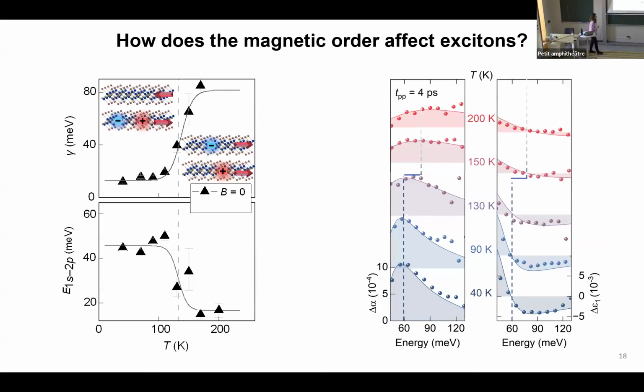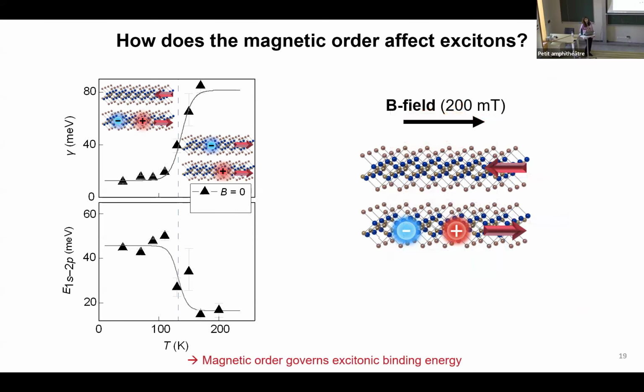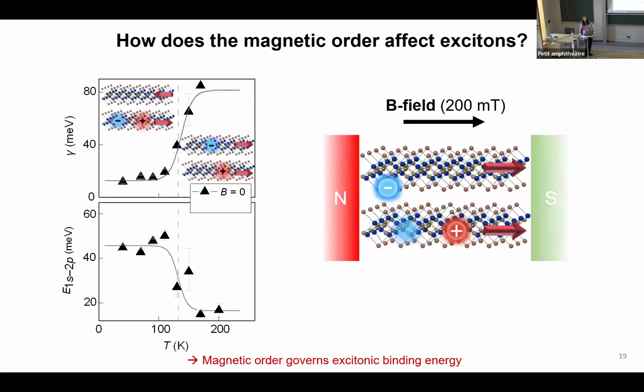So what are we learning here? We see that the magnetic field has a direct influence on the internal structure of excitons. In order to verify it with another step, to make sure that it is not a concomitant effect due to some single particle band gap renormalization across the phase transition, what we did is that we applied a magnetic field to our material to force the antiferromagnetic alignment to turn into a ferromagnetic alignment, and we repeated our measurements.